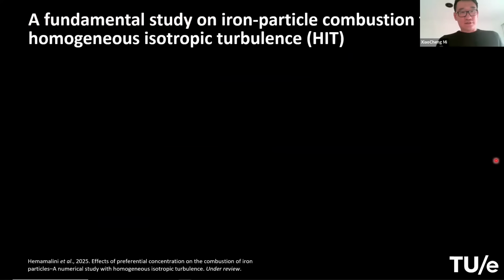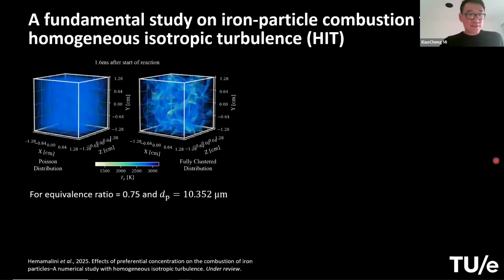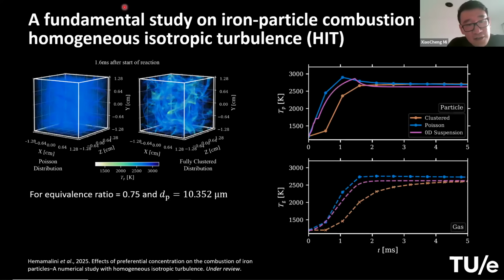We use this very fundamental way of constructing a box with homogeneous isotropic turbulence, HIT, and you put particles in there. You can see in this graph on the left is a random distribution, or Poisson distribution. And if you apply HIT to this box, the turbulence will concentrate the particles into these localized clusters. So if we set these two scenarios and let the iron particles combust in them, we can see the difference. And here are the differences.